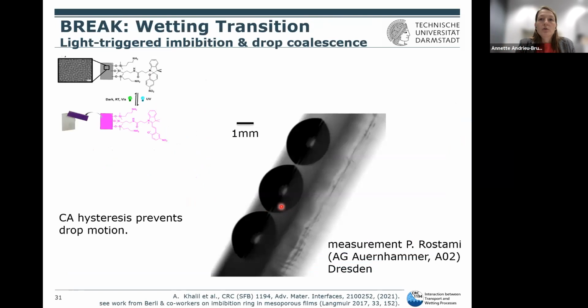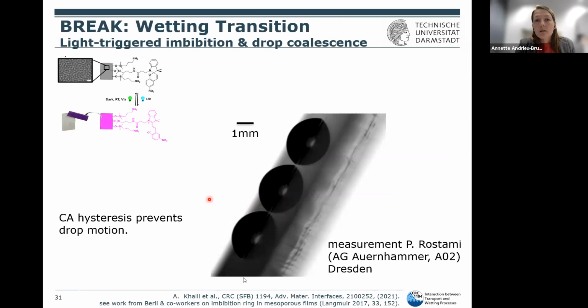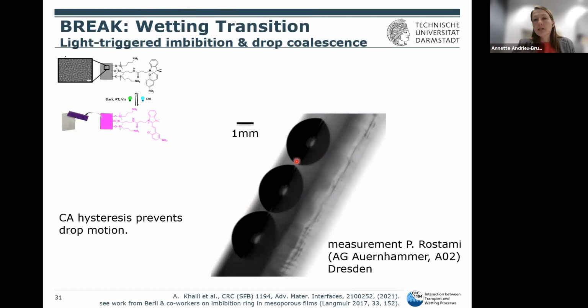And on the next slide, I will just show you a video on that. So what you would see is basically you have a tilted surface here. You would see that the light comes in, and then these droplets actually just merge and slide down the surface, not completely, because the drop volume was just not large enough to get it sliding down by gravity, but merging down here basically. So this is then an approach for how this functionalization, understanding of wetability in these pores and wetability transitions and polarity change upon irradiation can be used actually to get droplet coalescence induced and at the same time